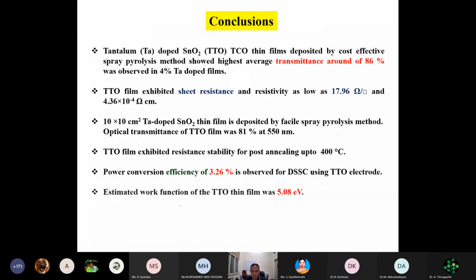So these values prove that TTO has transmittance around 86%, which is good for a TCO. Also the sheet resistance is very good, and this is for a particular green color wavelength, which is an average wavelength for visible radiation. It is good, and temperature stability is also 400 degrees centigrade. Whereas your FTO will have a temperature stability around 500 degrees centigrade.